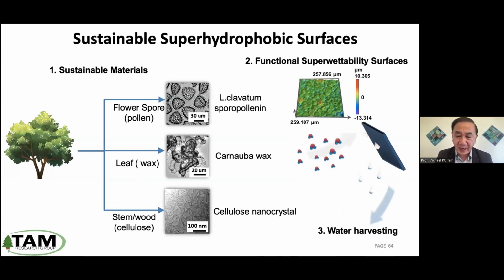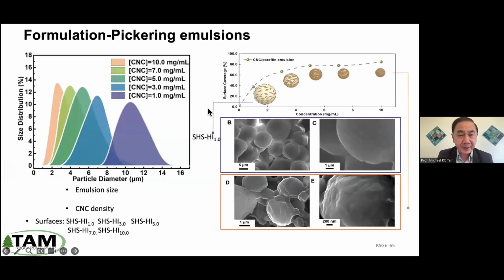So let me explain how we do it, right? So essentially what we did was that we take wax, we heat it to 60 degrees, it becomes liquid, we put CNC in the water, and then we emulsify. Right, and we make these wax droplets. They're about 3 to 30 micron in diameter. The more CNC you use, the smaller the particle, because there is more CNC at the surface. As you can see, the surface is quite rough. And we vary the amount of CNC from 1 milligram per mil to 10.